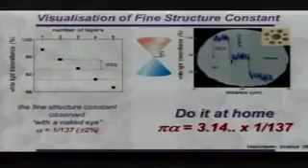What you see here is a special sample. We have an aperture in a metal scaffolding. We have absolutely nothing here, free space. There is graphene, there is bilayer graphene, and you can see a contrast here, and this contrast is about 2.3%. So one layer of atoms absorbs 2.3%. That's already quite surprising. Even more surprising that this number, 2.3%, is not just a number. It's actually the combination of the fundamental constants. It's exactly pi times alpha. Alpha is the fine structure constant, 1/137. Do it at home, 3.14 divided by 137, you get 2.3%.